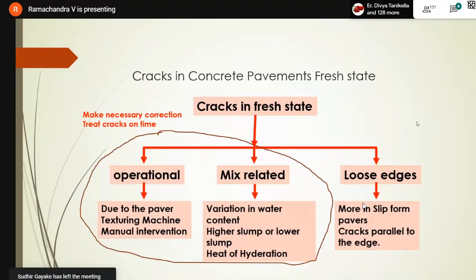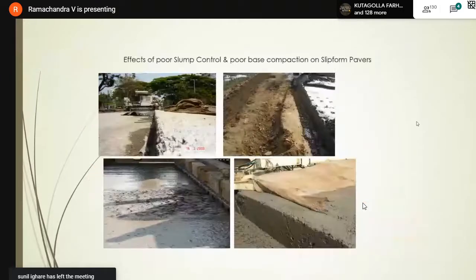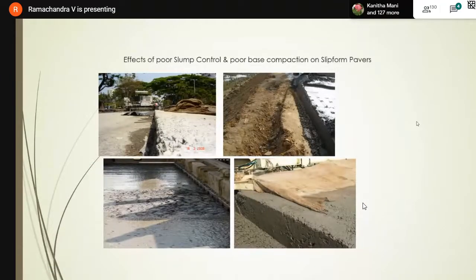Now, concrete in the fresh state, operational reasons, maybe due to the paver it may happen, maybe due to the texturing machine it can happen, and manual intervention also sometimes it can happen. Whereas in the concrete mix related, it can happen due to variation in concrete or higher slump content, or lower slump also can create this kind of thing. In case of high dosage of OPC, if you use 450 kgs of only OPC, the heat of hydration in concrete also can contribute to higher amount of cracks. Then finally, loose edges. In case of slip form pavers, this can happen, in concrete parallel to the edges. Only in case when you use slip form pavers. Now, this shows the effect of poor slump control.